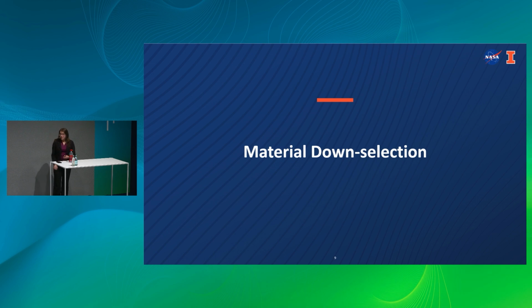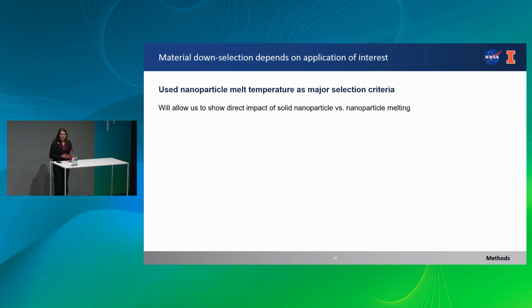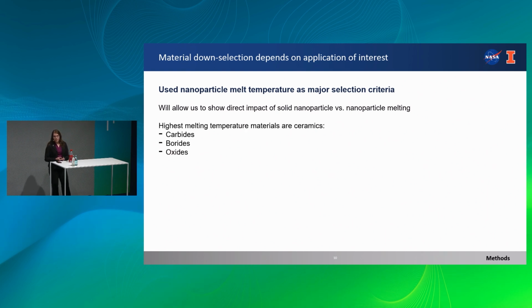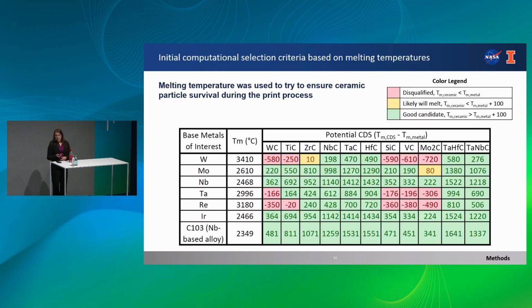So our first thought is, how do you decide what materials to use? So we actually used nanoparticle melting temperature as a major selection criteria, and this was just to help us tease out the impact directly of the nanoparticle versus potentially the nanoparticle melting. So we looked at some of the highest melting temperature ceramics, which are carbides, borides, and oxides. And as you can see here, when you take that into account, we mainly looked at the carbides because there's already a lot of oxygen in additive powder, and borides are particularly detrimental to nuclear applications. So we wanted to keep this general to a variety of extreme environments, like I mentioned.